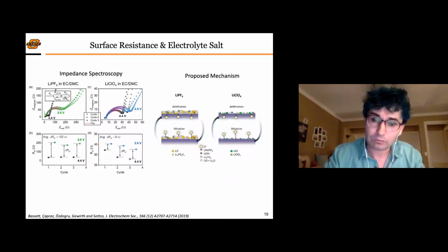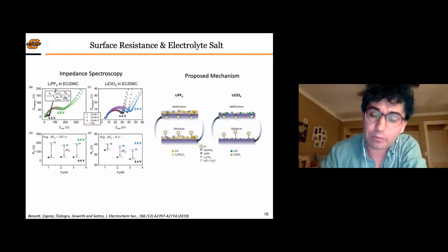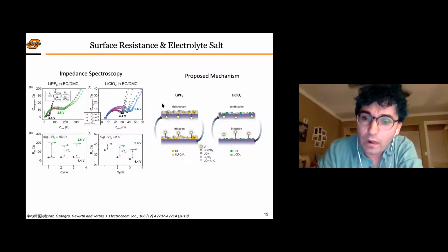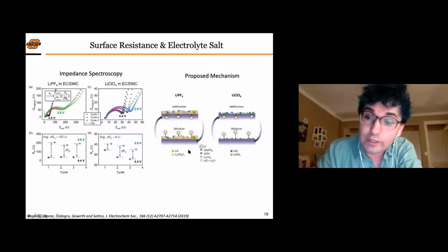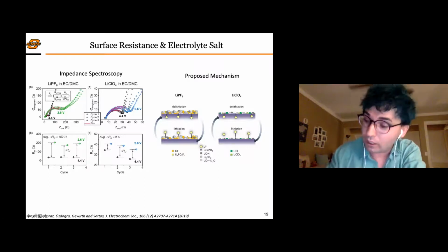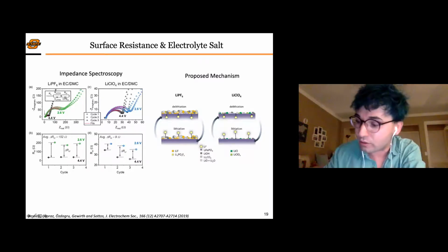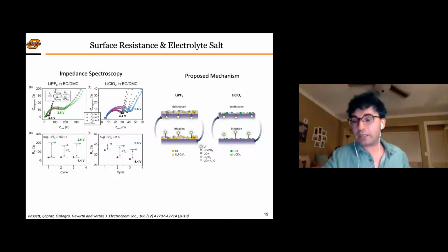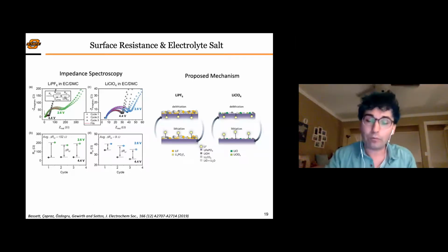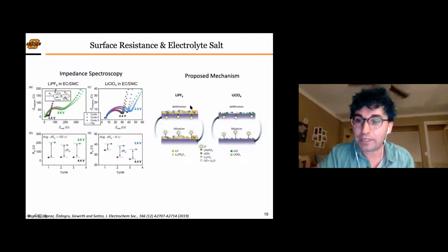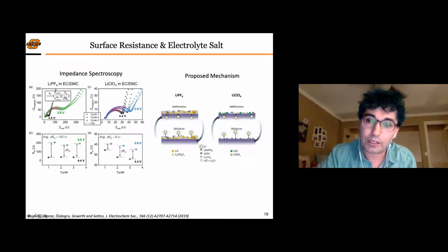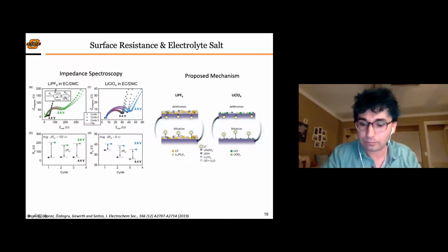electrolyte systems. We came up with a proposed mechanism showing that LiPF6 actually decomposes into more lithium fluorinated or lithium phosphate fluorinated components compared to lithium perchlorate. And when we look at the conductivity values from literature, we found that the conductivity of the SEI components in the LiPF6 is much, much lower than the conductivity of the SEI components formed in the lithium perchlorate.